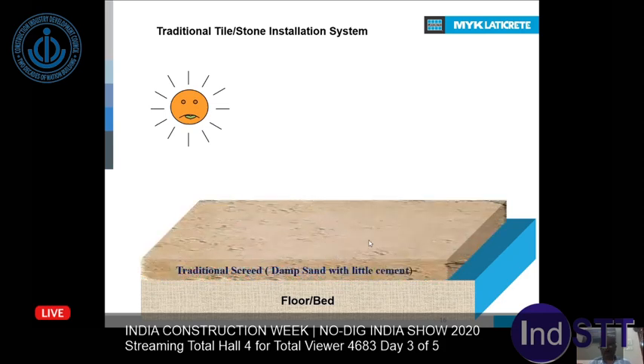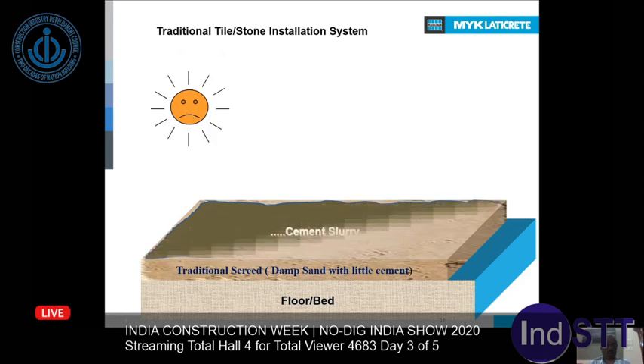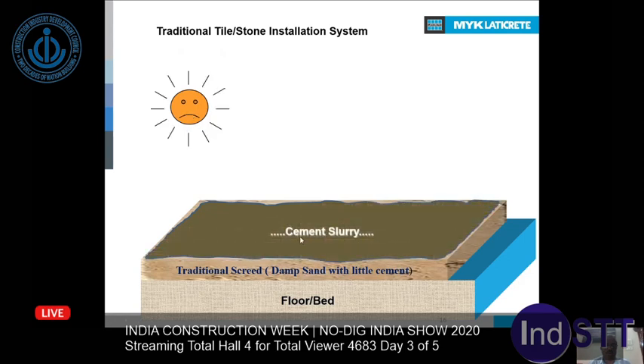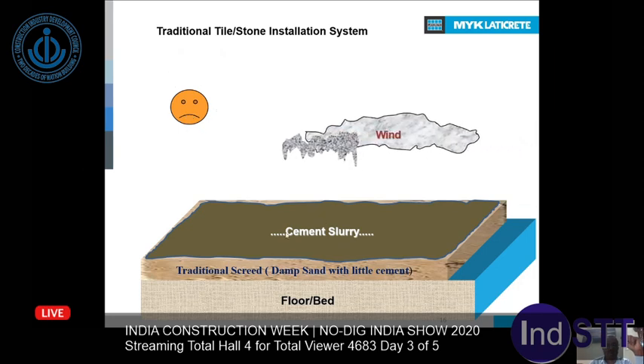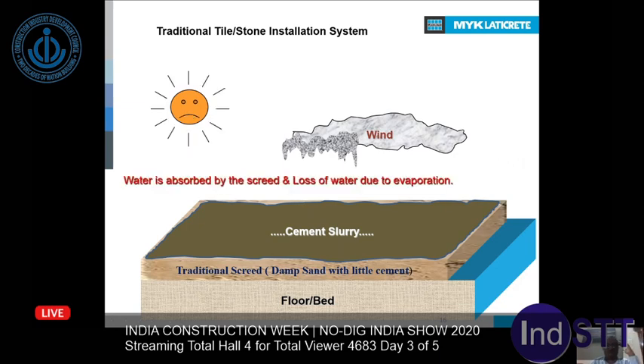The mason builds this up maybe 2 to 3 inches, 70 to 75 mm thickness. Then over it he sprinkles a cement slurry. This is basically nothing but normal ordinary Portland cement mixed with a good amount of water to have good workability, and he pours a very thin layer over this cement or sand bed. Again, these are all open conditions when the construction is happening in high-rise buildings, and the HVAC is still not running. It's open, hot weather conditions, and wind is also a factor.